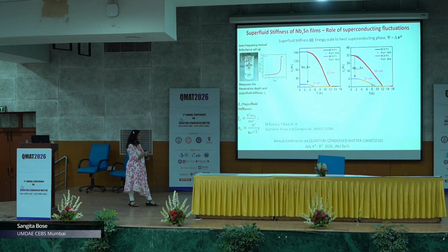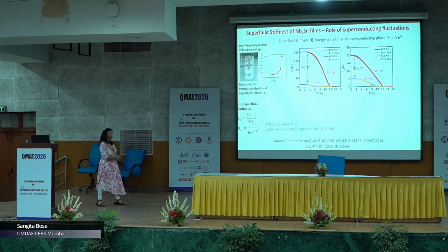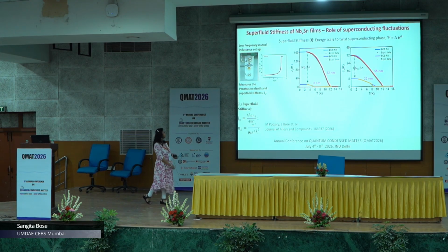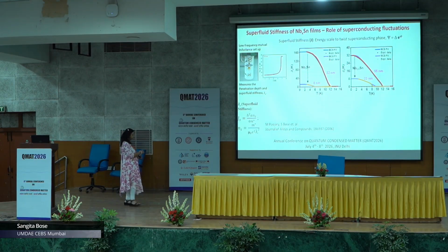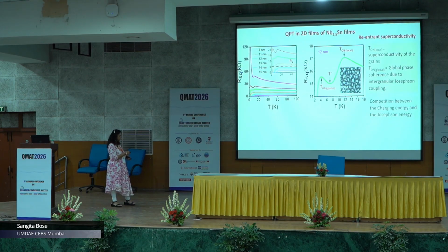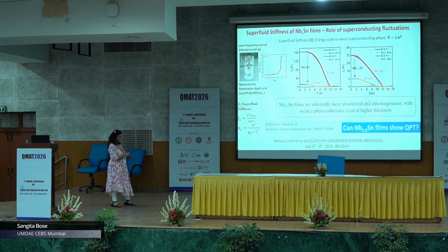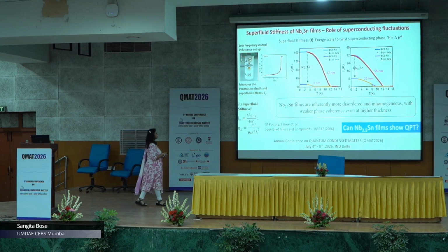What is important to note here is that for both the systems, as you reduce the film thickness, the superfluid stiffness decreases drastically. Well, this is not surprising, since our films are becoming more disordered, so you are getting an increase in the phase fluctuations, and the stiffness is decreasing. However, what we notice is that for films of about 23 nanometer, quite thick films, the stiffness has reduced substantially. It's almost comparable to what our 8 nanometer films in this series are showing.